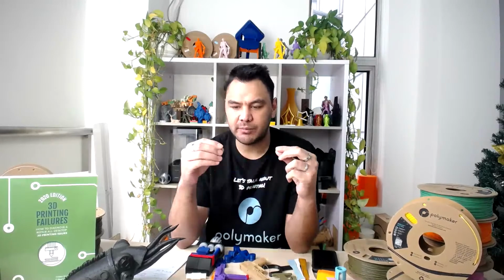Josiah says, oh yeah, I have this recycled HIPS that has no layer adhesion, even with no fan, at every temperature between 245 and 280, with a draft shield. Okay, so that has no adhesion, and how about the XY brittleness? If it's very brittle in XY, then it means the recycling, because recycling will lower the molecular weight of the material. Molecular weight means how long the chain is.